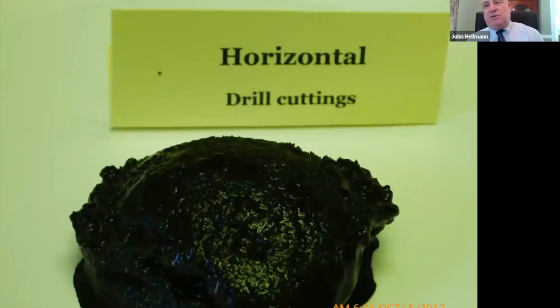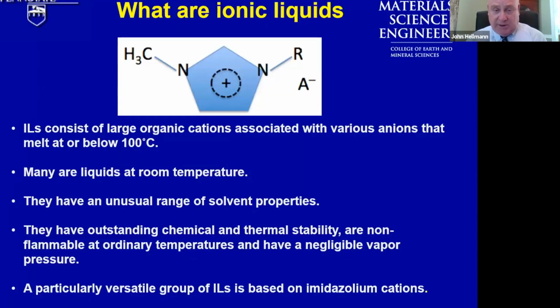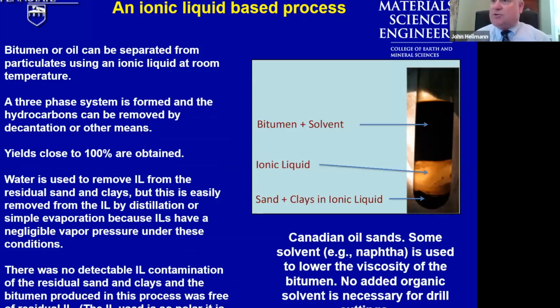The approach that we used was necessary because this is what a drill cutting looks like. When it comes to the surface, it's a black paste of shale particles suspended in mineral oil and containing other things like sandstone. We need to transform that into a dry powder particle for processing using conventional ceramic processing methodologies. We did it using an ionic liquid separation process that was being developed at Penn State for the tar sands programs. And this test tube on the right shows the result that you get when you use ionic liquid separation of bitumens from ceramic particulates like clay and sand.